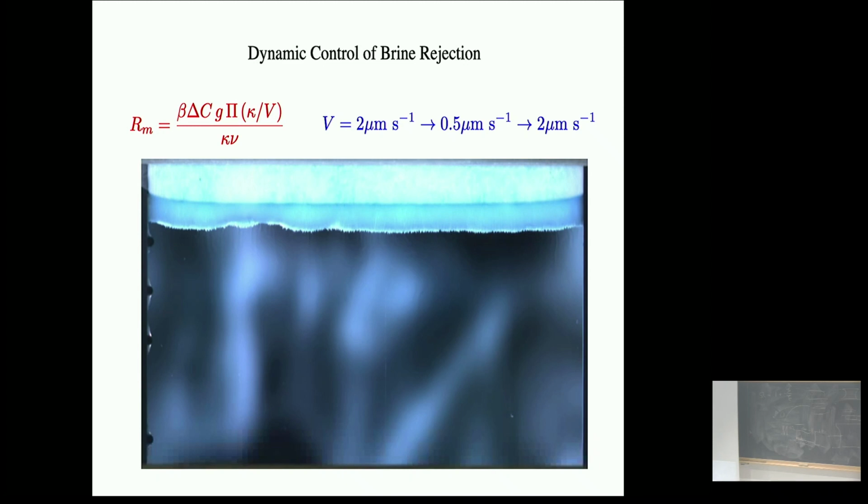The thickness of the mushy layer, by the way, sorry, let me just get your eye in. This is salt solution. The light blue here is mushy layer, and then this is about minus 21 degrees Celsius. This is colder than minus 21. So in this region, the ice is frozen and the salt is crystallized. This is completely solid. So we have completely solid, mushy region, liquid region. The Rayleigh number depends on the thickness of this region, and that thickness depends on the speed.